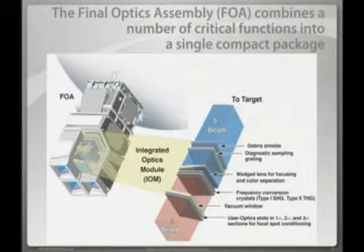Most importantly, we've had to develop optics that can take this 10 joules per square centimeter ultraviolet. Lasers like Nova, Omega, any lasers that are generally operating now, previously to NIF, operate at 3/4 of a joule per square centimeter. Just think about how big this laser would have been, actually it wouldn't have been, if you didn't have optics that could handle this kind of beating.